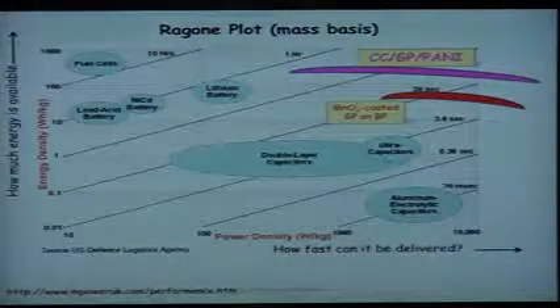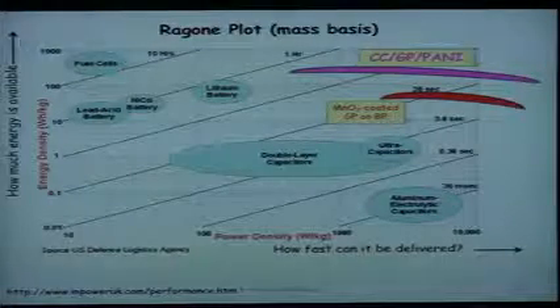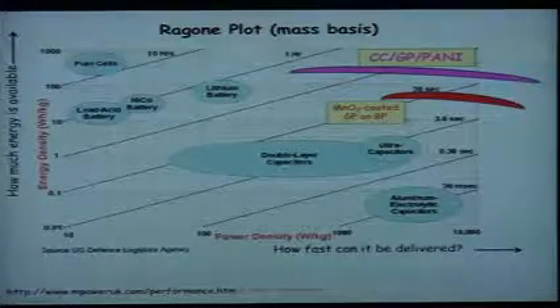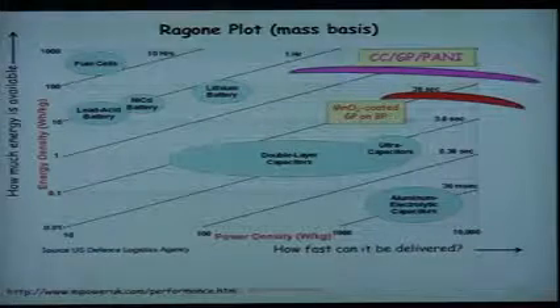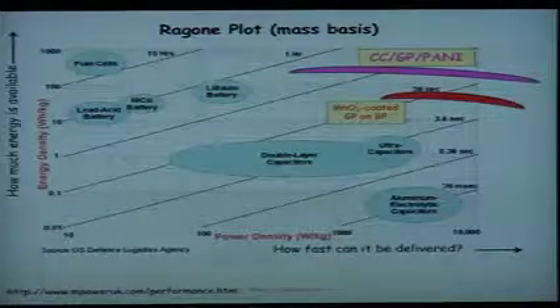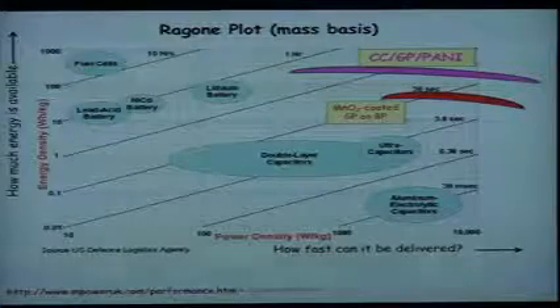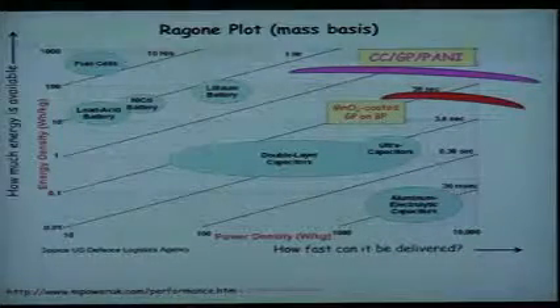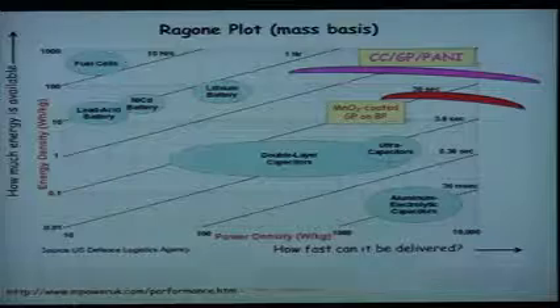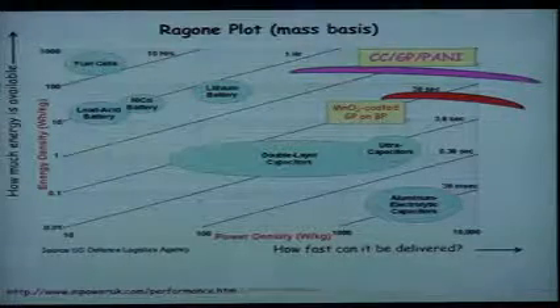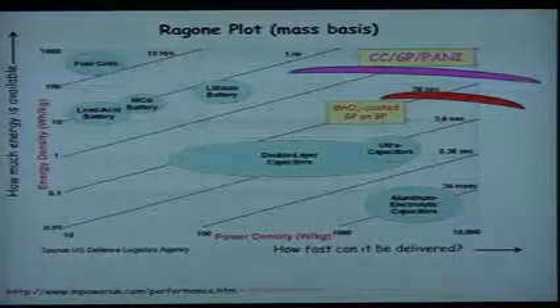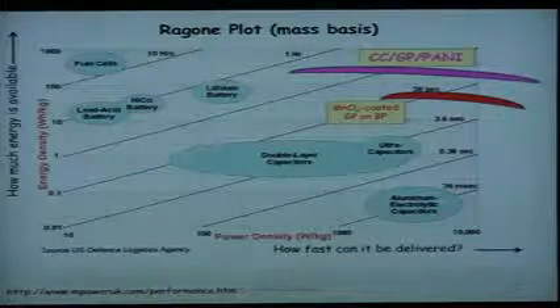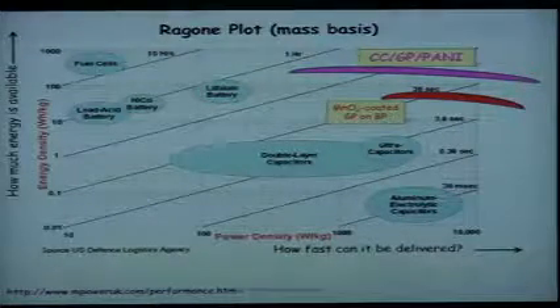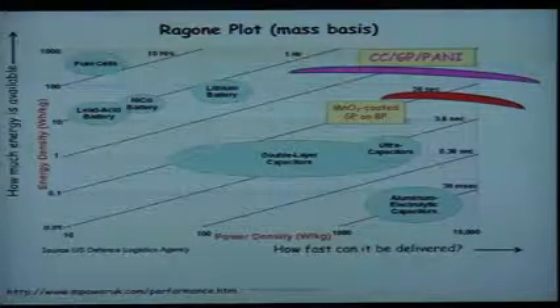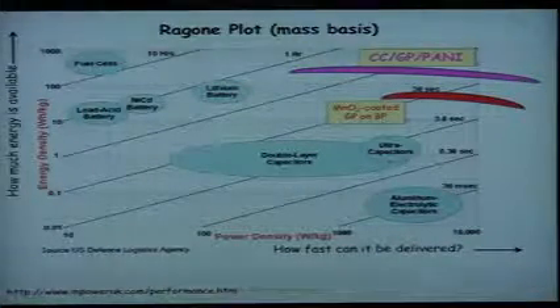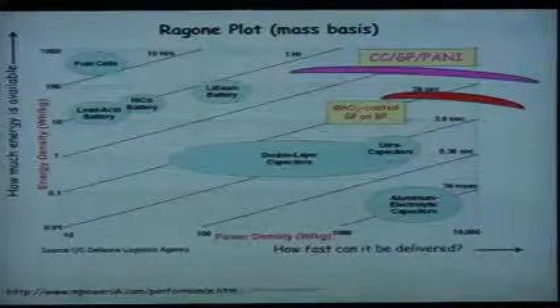The MnO2 pseudocapacitive material is a little bit worse in terms of energy density. Still not bad, though. It's comparable to lithium and nickel cadmium, lead acid. But it tends to have a higher power density, so it could go faster. All of these results came from where? There is no Ragone plot machine out there. It came from CV curves, charge-discharge curves, and the analysis that goes with it, right?